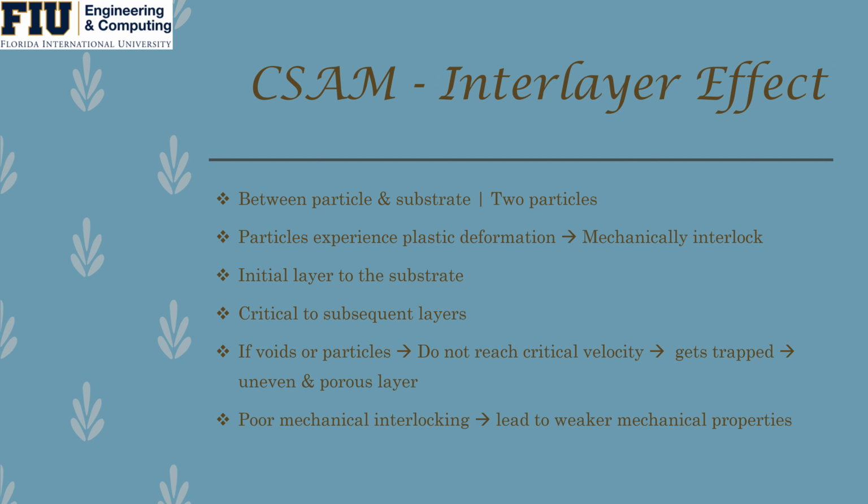Another key aspect of the CSAM system is the interlayer effect. This occurs between particle and substrate as well as particle and particle. As mentioned throughout this presentation, these particles experience plastic deformation to allow them to mechanically interlock with each other. It is very important that the initial layer on the substrate is uniform and free from porosity in order to have the subsequent layers also be uniform and free from porosity.